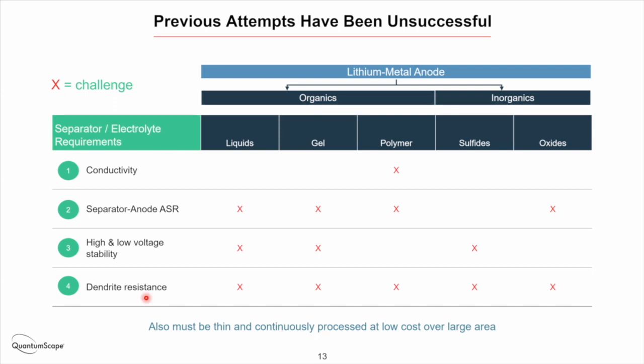Dendrites tend to form exponentially more aggressively as you increase the current density during charge. So as you go to a fast charge requirement, it becomes very difficult. And I'm not aware of any really compelling demonstration that a cell can resist dendrites over many cycles and realistic automotive conditions. So that's a big challenge. Then finally, the separator has to be made thin, comparable to today's polymer separators, and processed continuously, not in batch modes or high vacuum processing, to enable low cost over large areas. So it's really a difficult challenge.